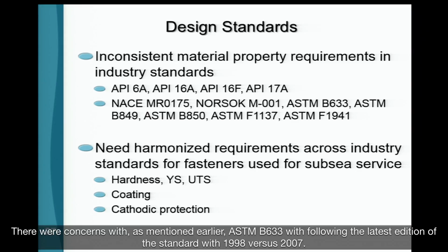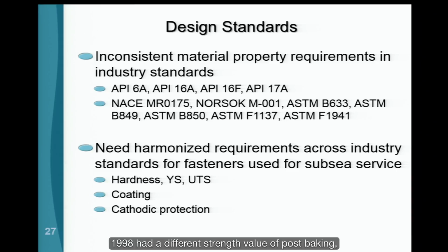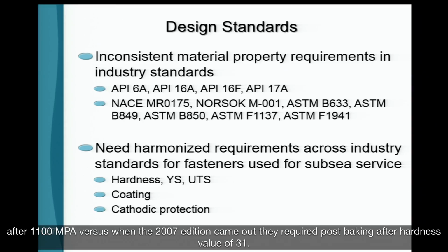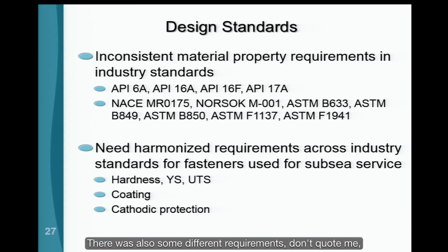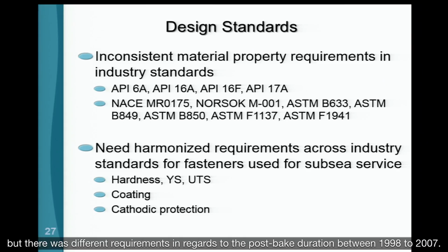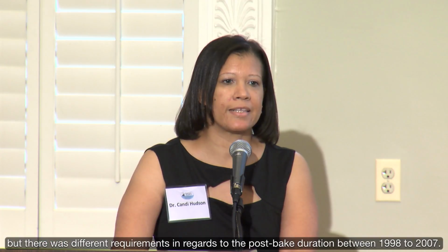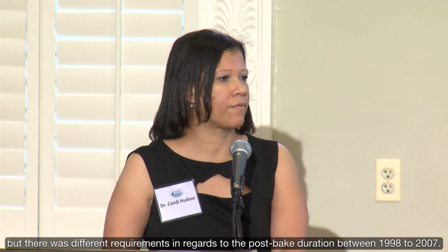There were concerns with, as mentioned earlier, ASTM B633 and following the latest edition of the standard, 1998 versus 2007. 1998 had a different strength value for post-baking, after 1100 MPa, versus when the 2007 edition came out, they required post-baking after a hardness value of 31. There were also some different requirements, don't quote me, but there were different requirements in regards to the post-bake duration between 1998 and 2007.